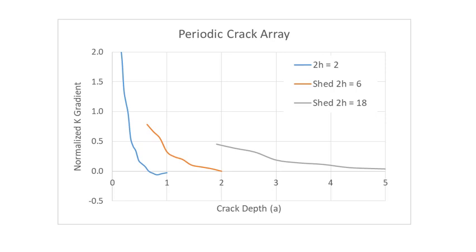Now this is a very, very important phenomenon because this is showing you that from a fracture mechanics perspective, and specifically from a crack stability perspective, your stress corrosion cracks, as they propagate, are increasingly shielding each other and are always in the process of stabilizing themselves by the sheer nature of the thermodynamics. And that's a very, very important thing. This tells you mathematically that your cracks will stabilize.